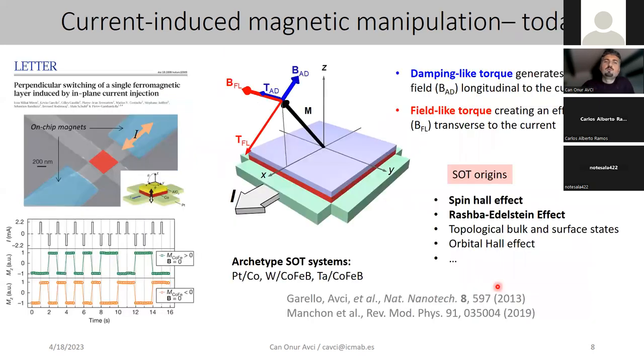But lately, there is a new trend. In the last decade at least, the new trend of controlling the magnetization relies on so-called spin-orbit torques. Spin-orbit torques have emerged as a powerful and versatile tool to control magnetization in a single ferromagnetic element, because in the case of a spin valve, you need two ferromagnetic elements and a lot of engineering. But with spin-orbit torque it is much easier, because you need a single ferromagnetic element and you need to send an in-plane current into that bilayer system, and you can already exert very strong torques, such as damping-like torque with this symmetry.